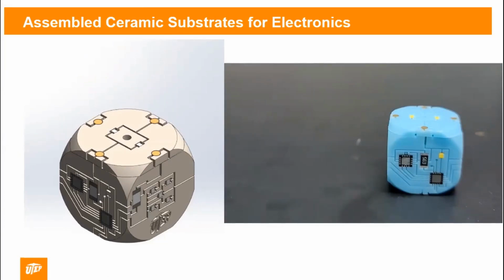But if you think about a tiered approach where you have this 1450 C sintering to get the ceramic to be full density or close to full density, then you put conductive inks into these traces and you fire those maybe at 850 C, so you get close to bulk conductivity. And then put in the electronics that can only go to say 200 C for 5 minutes or 150 for a long period. And then you have a third cycle to basically adhere the electronics to superficial edges. That's kind of an interesting idea, but you're limited to only surfaces that are external, obviously.